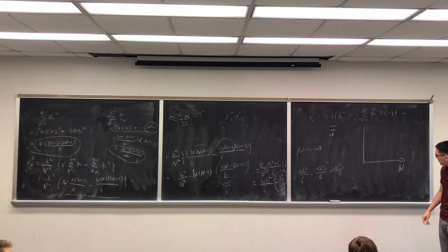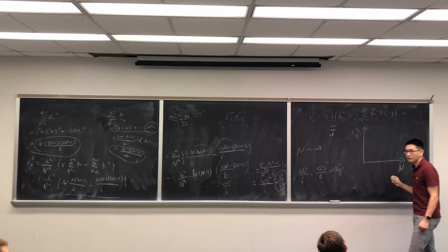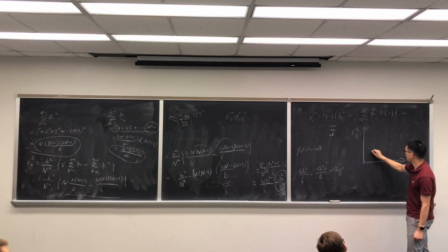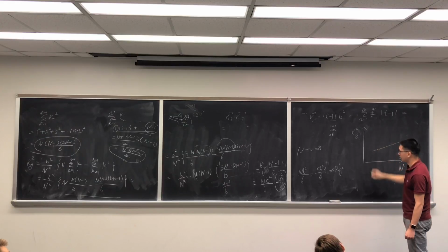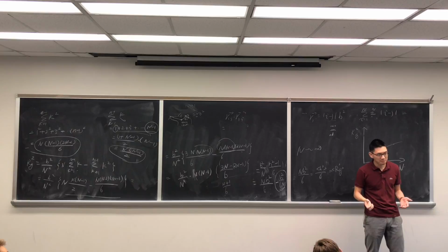And what you can do in terms of scattering is measure what Rg is. So what people typically do is this type of measurement, where they plot Rg squared versus n, and they can actually get information out. They can get these two pieces of information. Right?